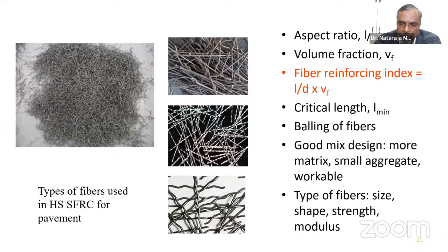So type of fiber, size of fiber, shape of fiber, strength of fiber, and modulus of fiber also play a very important role. So what is the meaning of strength and modulus? As the strength of the steel increases, the strength of the concrete increases. As the modulus of the fiber increases, the modulus of elasticity of the concrete also increases. But there are many instances where students have used polypropylene fiber or nylon fiber. They are all not high modulus fibers. And also, if you take the compressive strength or even the tensile strength of the fiber, it is not that good when compared to steel fiber.